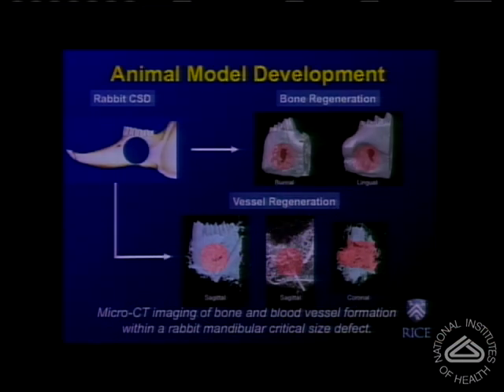For example, we can assess the quality of the blood vessels that are formed within the defect. This was our experience with the development of a critical size defect model in the mandible of a rabbit. So here we have a 10 millimeter bicortical defect. We can image, yes, the amount of new bone tissue that grows within that defect, but we can also image the number of blood vessels that can be formed within the biomaterial scaffold or in the absence of the biomaterial within that defect.